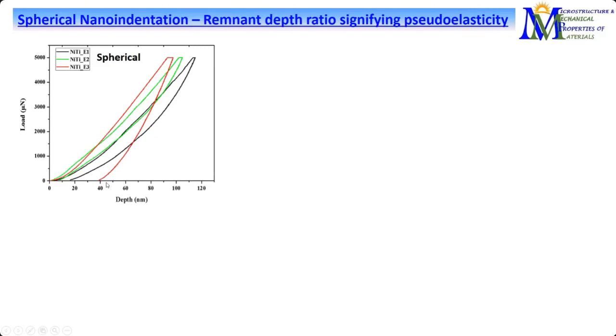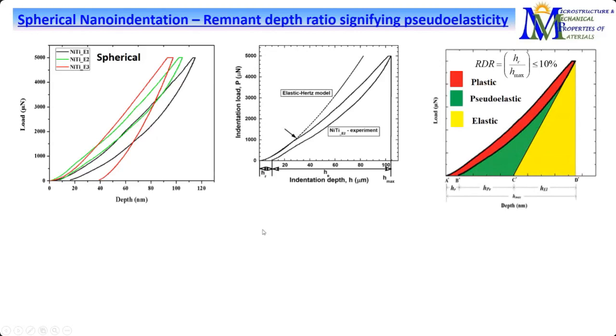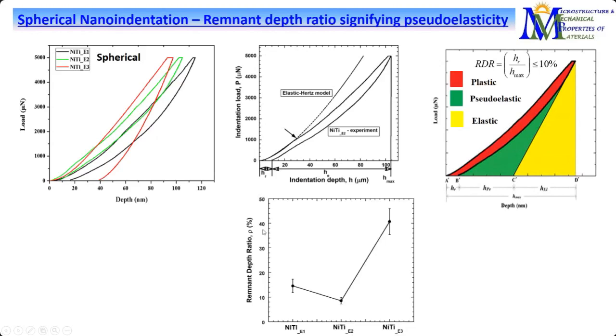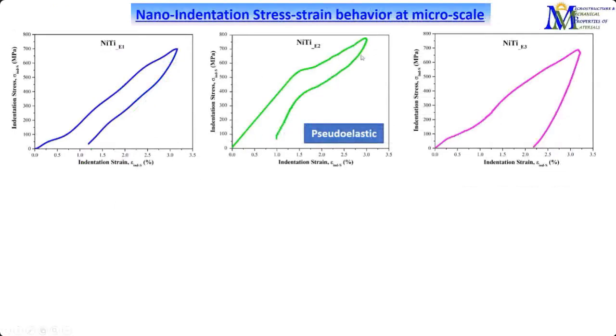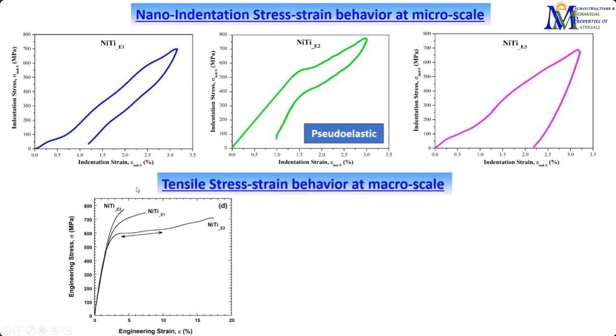Now, we require nickel titanium for applications which depend on its strain recoverability or shape recoverability, right? More than the strength, this is the critical property that we are concerned with. So obviously this study shows that if we use a moderate, lesser energy density while preparing, only then will we be able to recover the maximum amount of strain or load, shape basically. So this is what has been figured out, and we have found a way to draw the nanoindentation stress strain curve also.